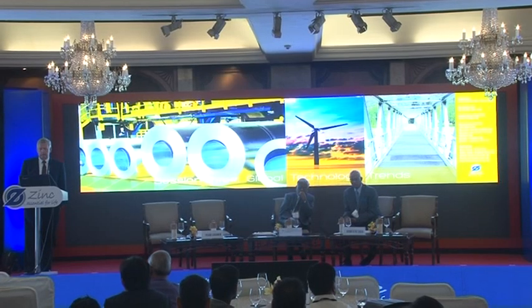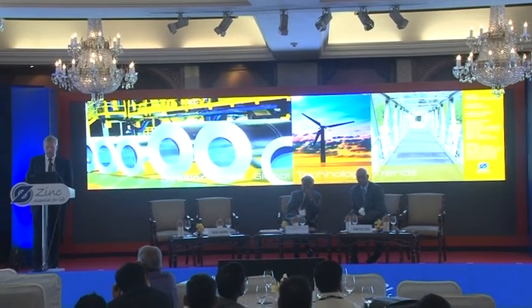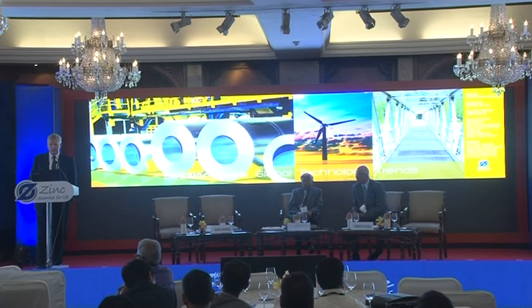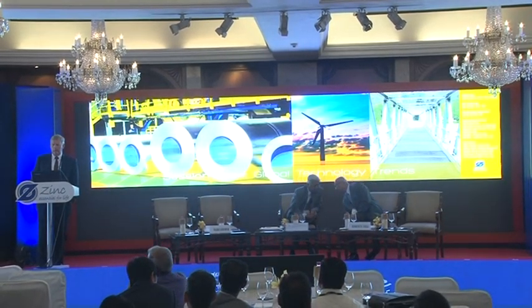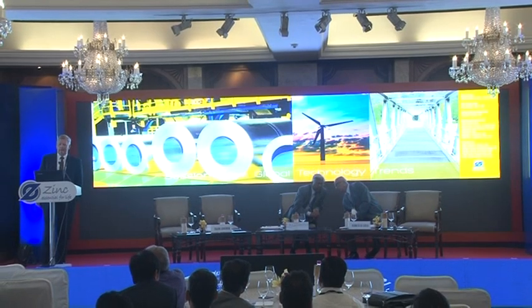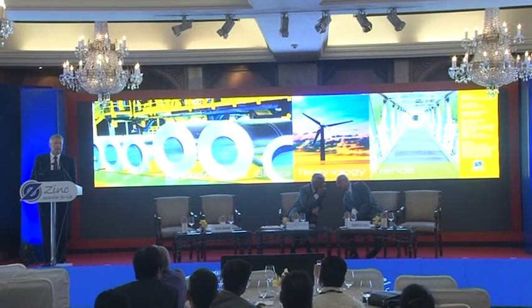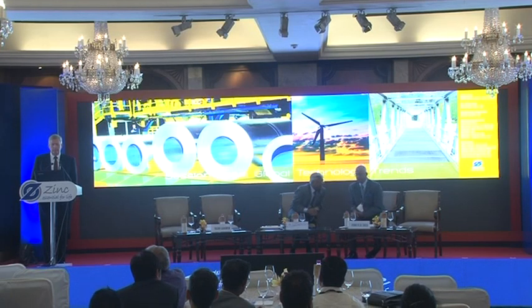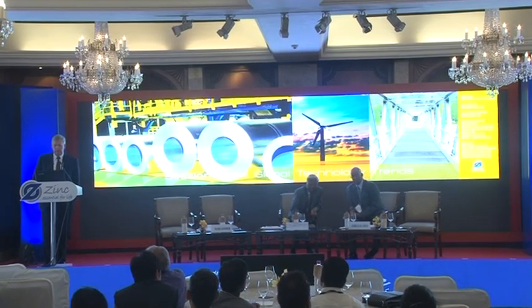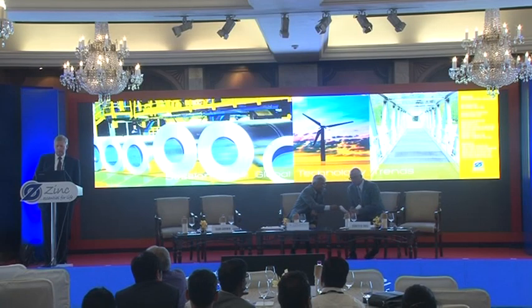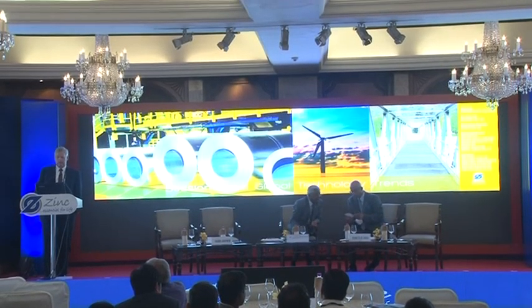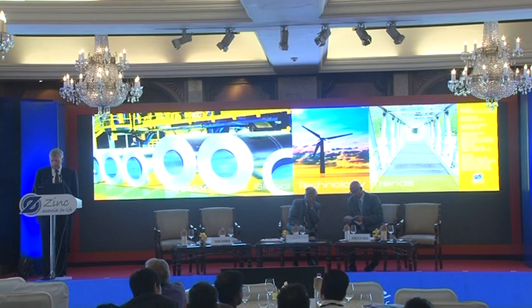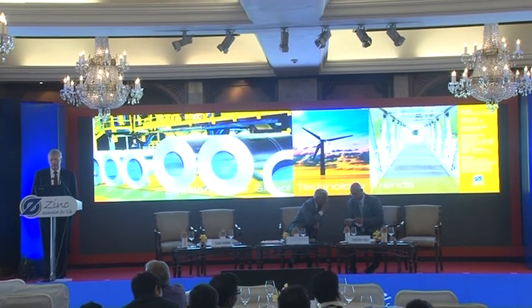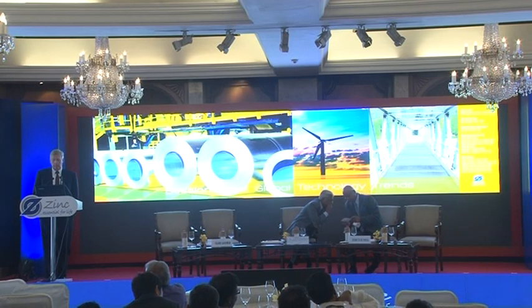And so a number of fatigue curves, the typical stress versus fatigue life or SN curves, were generated, and we showed that this quantified the effect of hot-dip galvanizing on fatigue strength for quite a number of steel grades that are used in bridge beams. And as a result of that, we did both these large and small scale tests and really didn't find any big change to what we already knew from the literature. And we now have in the German specification hot-dip galvanized beams for bridges.